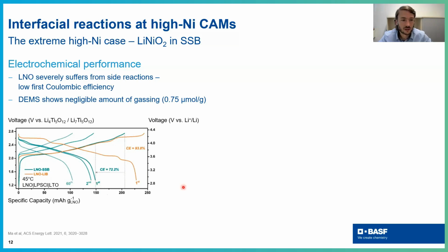Both of these materials are uncoated, and you see that for the conventional lithium-ion battery, you achieve around 93.8% of coulombic efficiency in the first cycle, meaning that essentially most of the lithium you are getting out of the cathode active material you can really put back in.